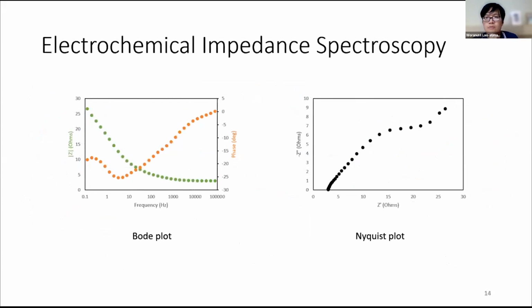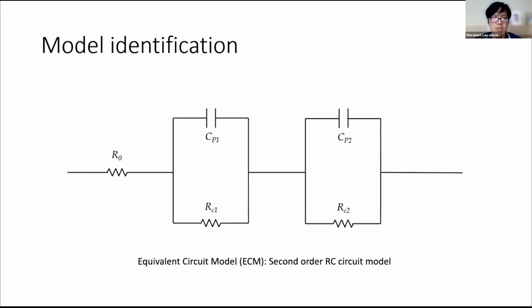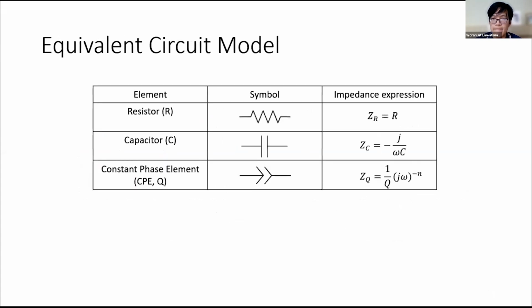The popular useful plots for EIS are the Bode plot and the Nyquist plot, which is the plot of imaginary impedance versus real impedance. These plots are used to fit with the model, which is the equivalent circuit model. The model that we use is the equivalent circuit model in the form of a second order RC circuit model, which is shown in this slide.